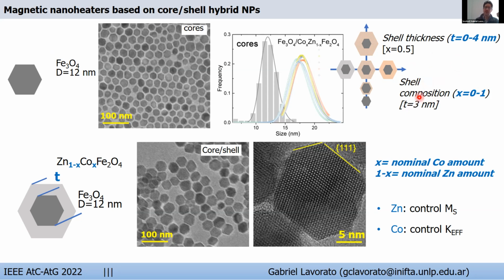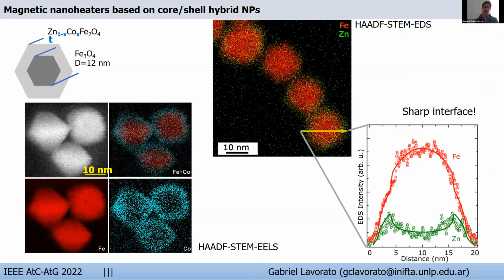We knew that the introduction of zinc allows us to tune the magnetization, while the cobalt increases the magnetic anisotropy of this shell ferrite. So we checked the narrow size dispersion by electron microscopy, and this kind of high resolution images confirmed to us that there is an epitaxial growth between the both phases. Then we confirmed also the core shell morphology by electron microscopy that nicely evidences a sharp compositional interface between core and shell, as shown in the images here. This means that there is no interdiffusion between core and shell.